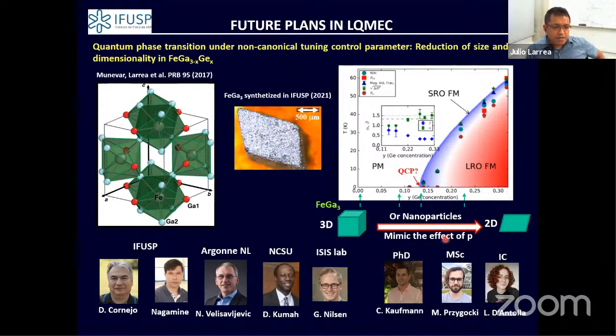And we actually selected one system, iron gallium 3, doped with germanium, in which, in a previous investigation, we saw that by simply substituting gallium by germanium, you induce a non-magnetic state to a magnetic state, right? Passing possibly, or likely, through a quantum critical point, which is still an open question. But the way that we are trying to approach this investigation, by using a non-canonical tuning control parameter, will give us a more straightforward evidence of how quantum critical behavior actually appears at a more reduced atomic scale.